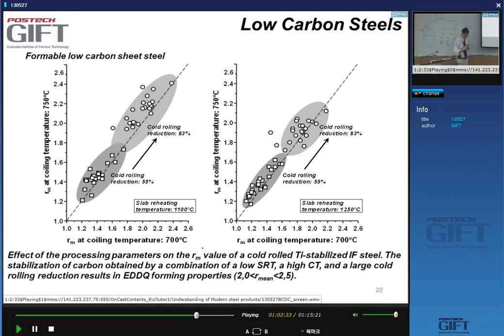I don't want to give the impression that for titanium steels or titanium-niobium steels, which we call interstitial-free steels, there are no issues related to sensitivity to processing parameters. On the contrary, they're also there, because we still need to form these precipitates. Titanium nitride is usually not a big issue: extremely low solubility, a very stable precipitate, and it forms almost readily and fully. But that is not the case with the precipitation of the carbides in the IF steels.